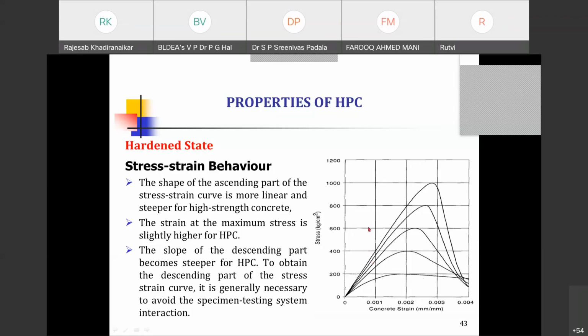This behavior is basically because high performance concrete exhibits less internal microcracking compared to conventional concrete. So this distinct behavior is observed. In very low grade concretes, you have a totally curvilinear behavior, and the ultimate stress and the peak strain are different. As the strength increases, the linear portion increases, and the stress level to which this linear portion reaches is also higher. In conventional concrete it is normally around 20 to 30%, and for very high strength concrete it goes even up to 60% of its ultimate strength.